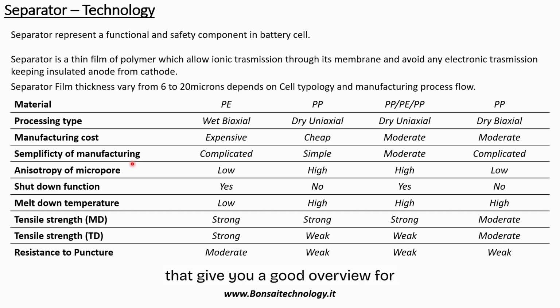I think this is a very important slide that gives you a good overview of the separator technology and separator features. As mentioned before, the main components of the separator layer are polyethylene and polypropylene, or just polyethylene or just polypropylene, or a combination of the two in a multi-layer separator. The manufacturing type could be wet or dry. As you can see, there are some pros and cons that later on we are going to explain. And even the stretching process could be axial, uniaxial, or biaxial.